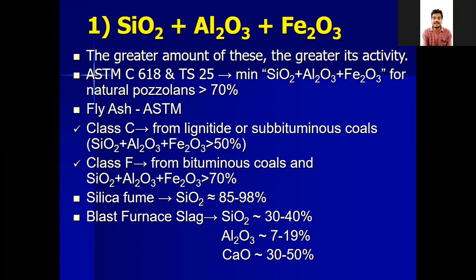So you call it silica fume when the pozzolana cement consists of 85 to 98% of SiO2. You call it blast furnace slag when the SiO2 content is between 30 to 40%, Al2O3 from 7 to 19%, and calcium oxide from 30 to 50%. So in these different ranges, we are calling those silica fume, blast furnace slag, Class C pozzolana cement, or Class F pozzolana cement. Hope you understand.